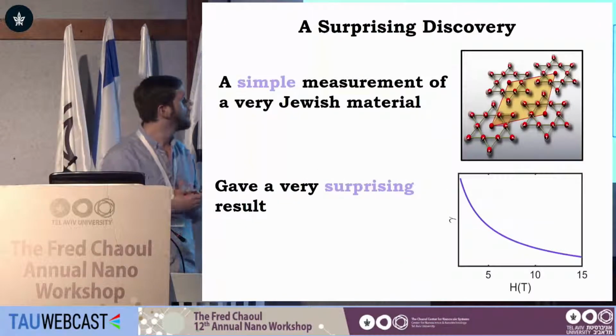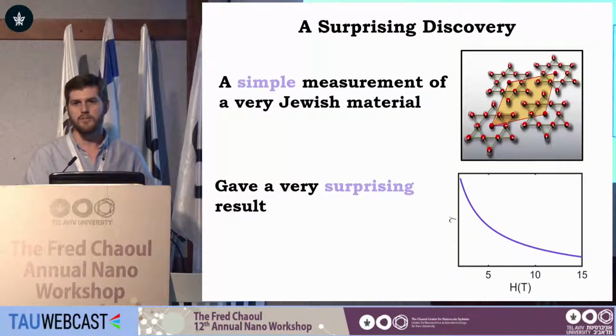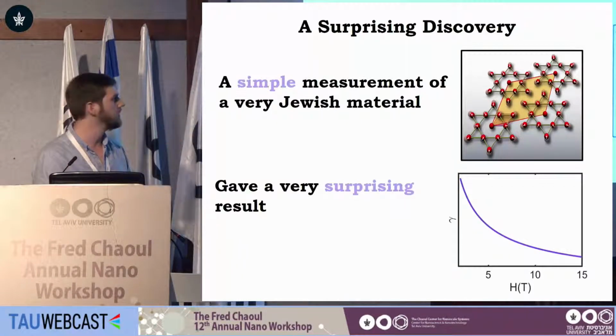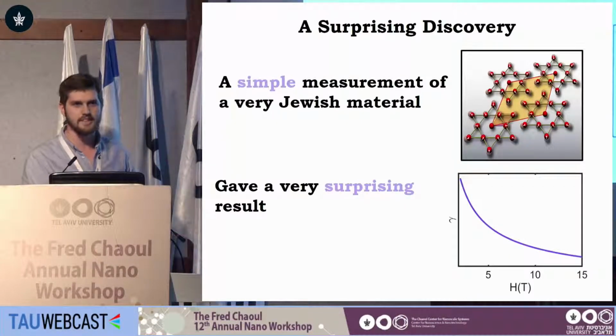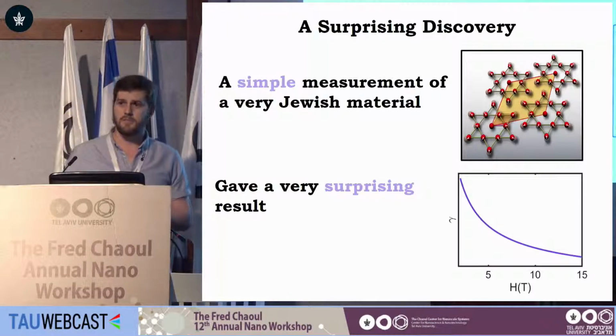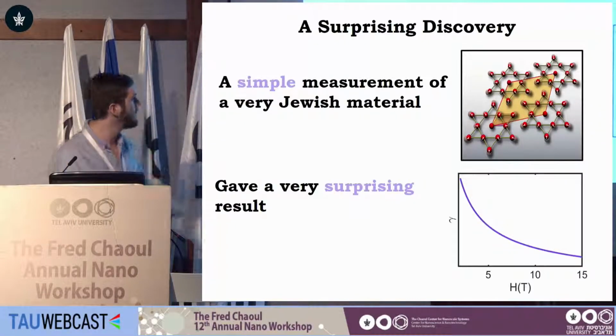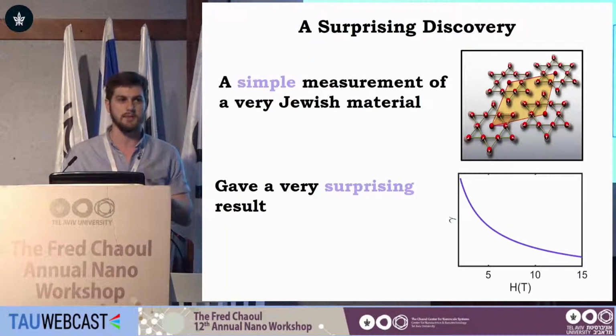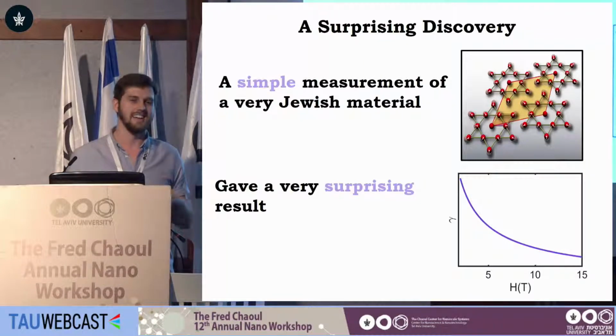So I worked with a very nice material, tantalum sulfide. It orders in a 2D layer of those little stars of David. And I made a simple measurement of the heat capacity of that material. And that very simple measurement gave a very surprising result. You see a graph here of a term named gamma. It was supposed to be 0 all along. It was not. And moreover, it even depended on the applied magnetic fields.